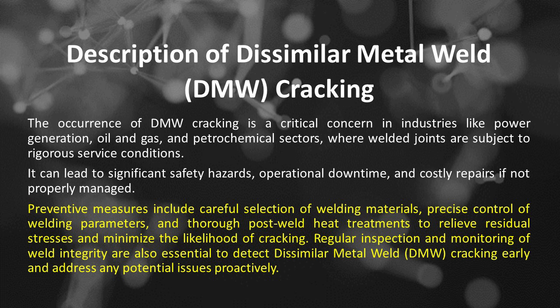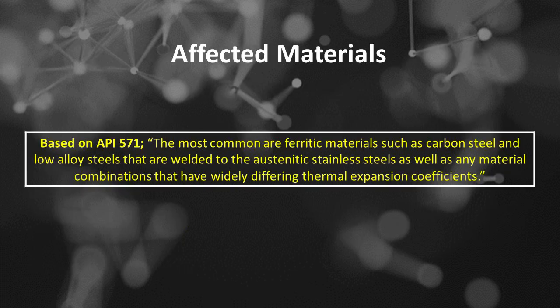Regular inspection and monitoring of weld integrity are also essential to detect dissimilar metal weld, or DMW, cracking early and address any potential issues proactively. Dissimilar metal weld, or DMW, affected materials based on API 571. The most common are ferritic materials such as carbon steel and low-alloy steels that are welded to the austenitic stainless steels, as well as any material combinations that have widely differing thermal expansion coefficients.